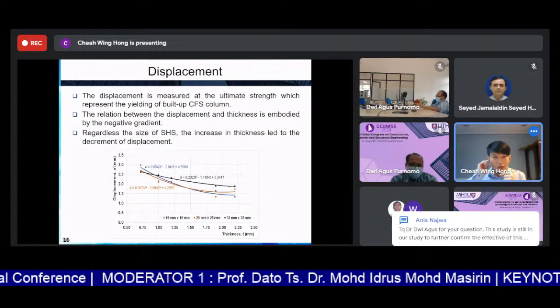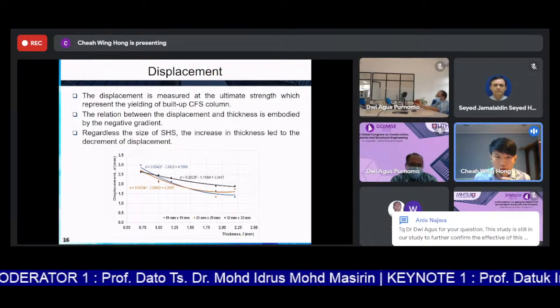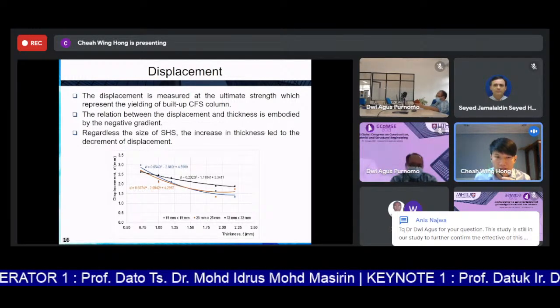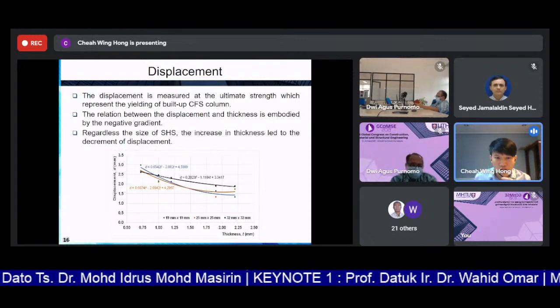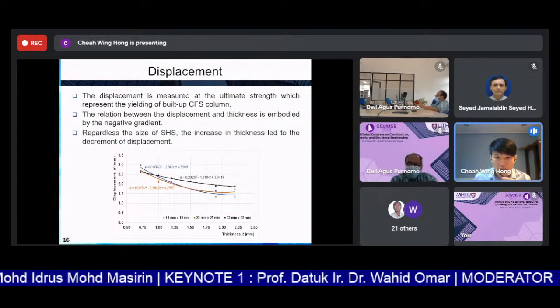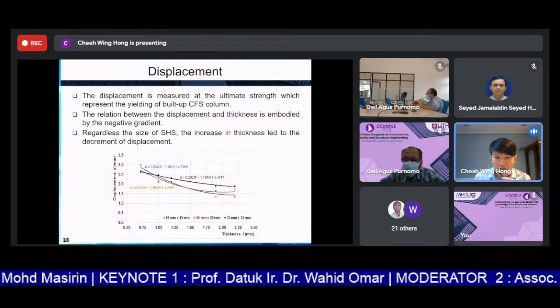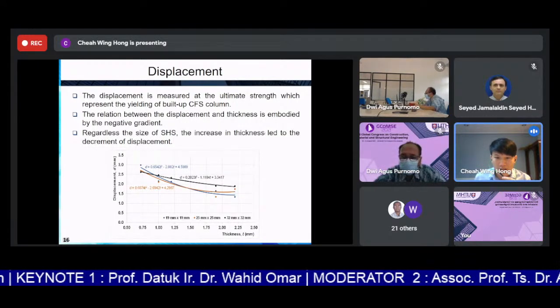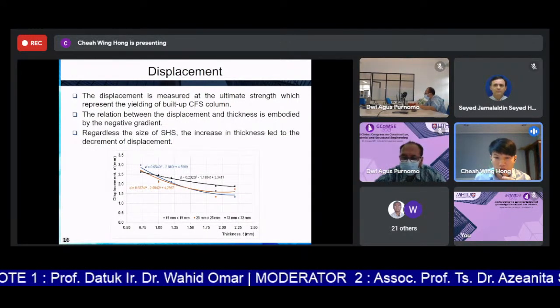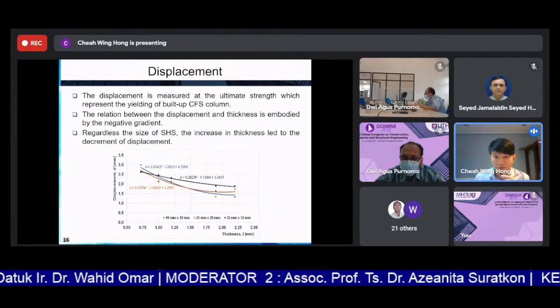So the displacement is actually measured at the ultimate strength, which represents the yielding of the built-up CFS column. And the relation between the displacement and thickness is embodied by the negative gradient. Regardless of the size of the SHS, the increase in the thickness is actually leading to the decrement of the displacements of the built-up CFS column.